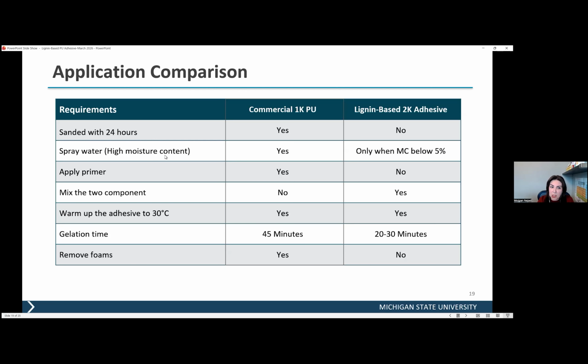We only recommend spraying water if it's been very, very low moisture content, below 5% or so, which doesn't usually happen. And then for the 2K adhesives, again, in some formulations, they recommend that you apply primer. What we don't need is primer applications for the lignin-based adhesives.